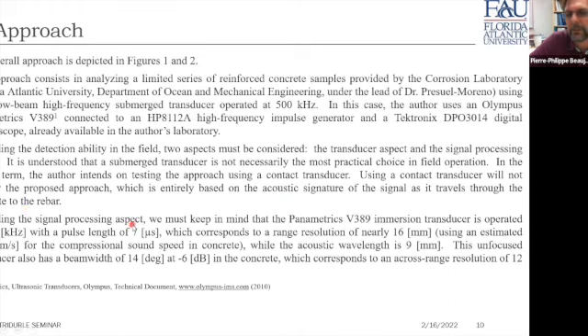Now, regarding the signal processing aspect, we must keep in mind that the V389 immersion transducer is operated at 500 kilohertz with a pulse length of 7 microseconds, which actually corresponds to a range resolution of nearly 16 millimeter, using an estimated 4,500 meters per second for the compressional sound speed in concrete, while the acoustic wavelength is 9 millimeter. This is an unfocused transducer, which has a beam width of 14 degrees at -6 dB in the concrete, which corresponds to an across range resolution of 12 millimeter.